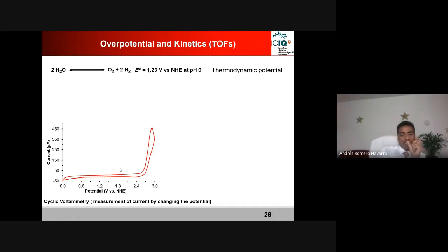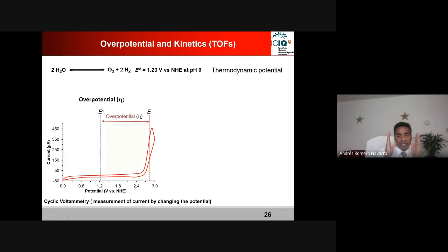And here I'm showing what is called the cyclic voltammogram. The cyclic voltammogram is a technique where you are measuring the current by changing the potential of the system. So imagine that this E0 value is showing the thermodynamic potential for doing this water oxidation. That value is 1.23 volt. So to do this, you need a minimum of this much potential. But let's say you have a catalyst that is showing this activity. You can see when there is an enhancement of the current, that is an indication that you are doing this oxidation. So here, let's say you are doing water oxidation, and the real applied potential is now here. The difference between this thermodynamic potential and the applied potential is called the overpotential.